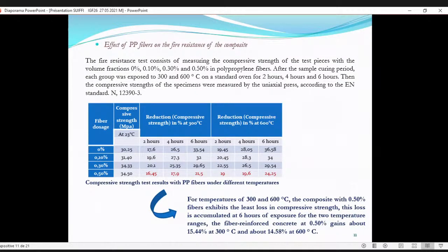For the part on the effects of PP fibers on the fire resistance of the composites, the fire resistance test consists of measuring the compressive strength with the volume fractions 0%, 0.10%, 0.30%, and 0.50% of polypropylene fiber. After the same curing period, each group was exposed to different temperatures, 300 and 600 degrees Celsius, and we measured the compressive strength. Here in the table, we can see the value of the reduced compressive strength in percentage at different temperatures.